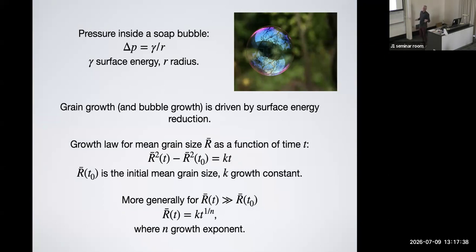So the grain growth law that has been first derived in material science, a lot of that comes from material sciences. So grain growth law, you have a mean grain size that then increases over time. And you can derive an equation like this. So mean grain size squared as a function of time minus the initial grain size at some starting time is characterized by a growth constant and then time. Right? So as time ticks up, the mean grain size here increases. And if your starting grain size is small enough, because often you don't know your starting grain size very well, for mean grain size is large enough, you can just ignore that. And so the grain growth law becomes fairly simple. You have the mean grain size as a function of the growth constant, and then this exponent. So that looks fairly straightforward enough.